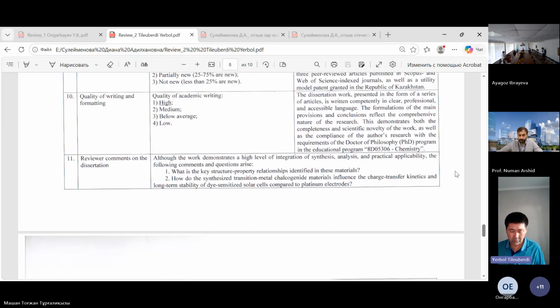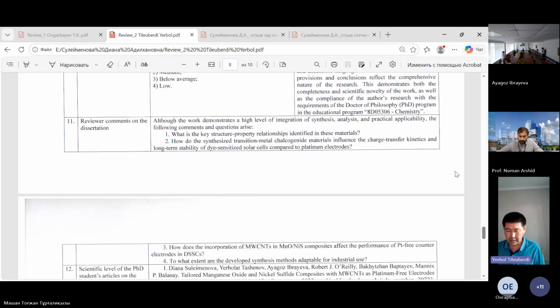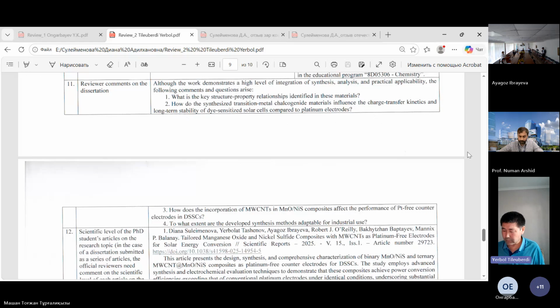So next, reviewer comments on the dissertation. I have 4 comments for this dissertation. First is: what are the key structure-property relationships identified in these materials? Second, my comment is: how do the synthesized transition metal chalcogenide materials influence charge transfer, kinetics, and the long-term stability of dye-sensitized solar cells compared to platinum electrodes?